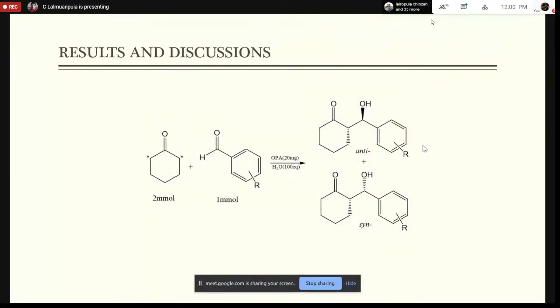Among the 3 aldol donors, aldol donor B, that is cyclohexanone, has 2 prochiral centers marked with stars. Therefore, the reaction generates 2 chiral centers, which results in a racemic mixture of the 2 diastereomers, syn and anti. This makes the reaction really interesting as diastereomeric selectivity comes into play.